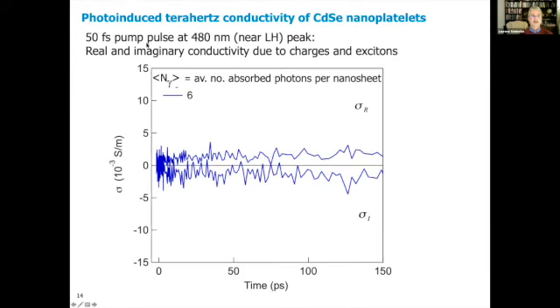Now, we photoexcited these nanoplatelets at 480 nanometer with a short 50 femtosecond pump laser pulse, and we measured the real and the imaginary conductivity due to charges and excitons. Now, this is the conductivity. In the upper panel, I show the real conductivity. In the lower panel, negative, the imaginary conductivity. Here we photoexcited the nanoplatelets with on average 6 photons. And then we see a small real conductivity and a small imaginary conductivity, which hardly decay, or in fact don't decay on the 150 picosecond timescale here, because the lifetime of excitons exceeds tens of nanoseconds.